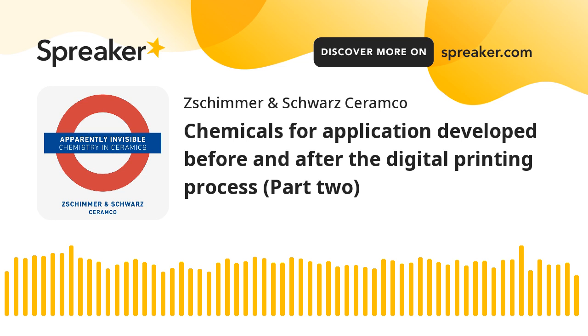Let's now turn the page and change chapter by addressing the watery applications that take place after the digital printing process, that is, the application of grit or glaze suspensions. In all these cases, the most common problem is the incompatibility between the solvent-based inks that, in general, are made of non-polar polymers and the end-of-line watery applications that contain water that is polar solvent.